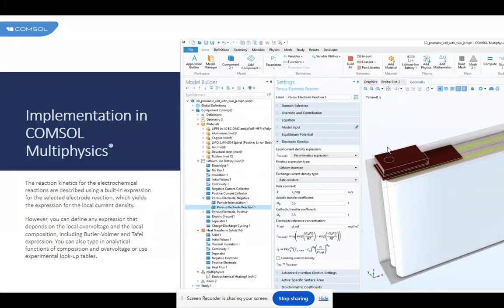The reaction kinetics for the electrochemical reactions are described using a built-in expression for the selected electrode reaction, which yields the expression for the local current density. However, you can define any expression that depends on the local overvoltage and the local composition, including Butler-Volmer and Tafel expressions. You can also type in analytical functions of composition and overvoltage or use experimental lookup tables.